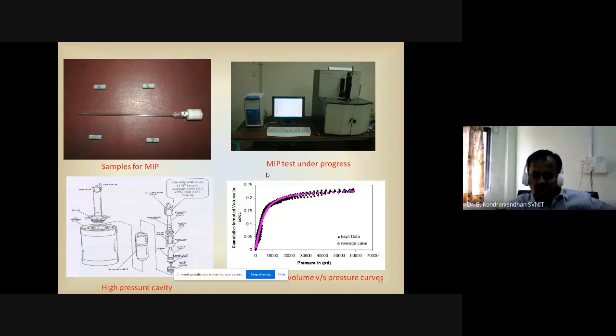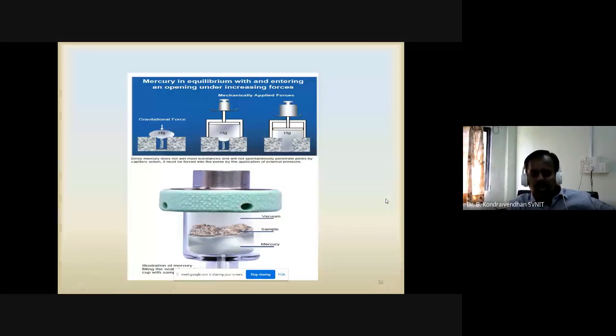Then we have to take the average, so we are taking the average curve. Now there are 3 experimental data and one average curve also done. All are in cumulative intrusion volume versus pressure curves. That's how we have to perform the mercury intrusion porosity test.